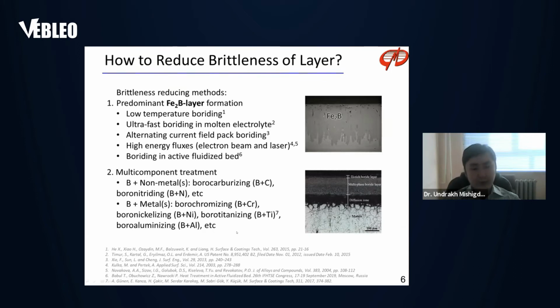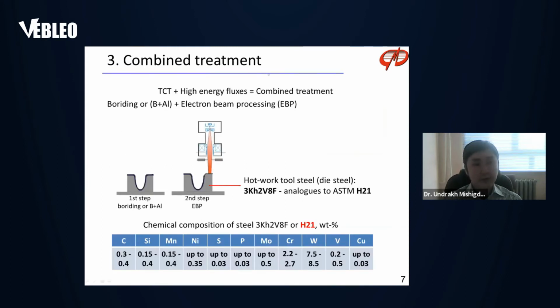The latter method is a combination of boriding and aluminizing, where iron borides provide high mechanical properties such as wear resistance and high microhardness, while the iron aluminides provide high oxidation resistance at high temperatures and plasticity for the entire layer. The third method of reducing brittleness is combined treatment, where thermal-chemical treatment can be done as a first step, followed by high-energy flux treatment.